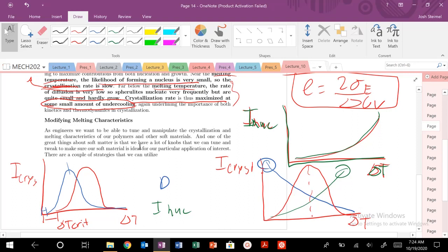to start to nucleate. Similarly, depending on your polymer, as we're going to see in a bit, these curves can shift as well. So a polymer that's much more flexible and wiggly, and wants to maximize its conformational energy states, you're going to have to put a lot more energy in, i.e. a larger delta T crit, than a polymer that is shorter, more rigid, and will want to fold. It'll be easier to stack those particles. Or a polymer that has much more favorable non-specific or specific enthalpic intermolecular interactions, like H bonds or polar groups, et cetera. So that's basically it for crystallization rate.